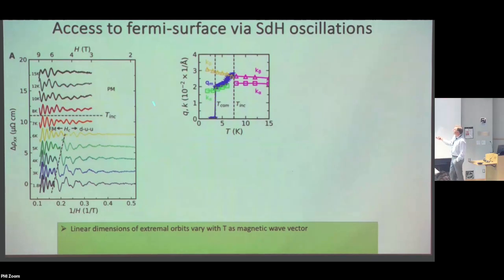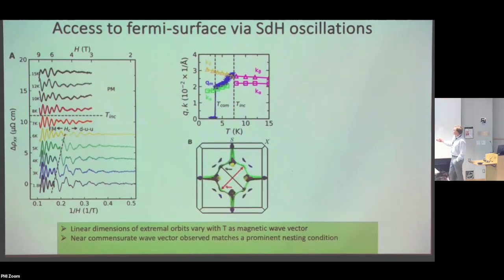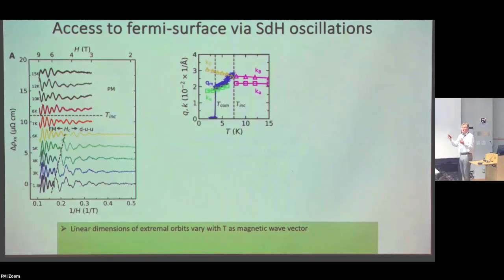So there are Shubnikov-de Haas oscillations, and from those we can extract the area of the extremal orbits, and from that we can extract a characteristic linear dimension of the orbit. So I take a square root of the area, I get some kind of characteristic linear dimension, and then I can follow the temperature dependence of that linear dimension of a particular orbit on the Fermi surface, and we find that that temperature dependence has a similar sort of slope. So dq/dT is similar to what we observe in terms of the temperature dependence of the antiferromagnetic wave vector.